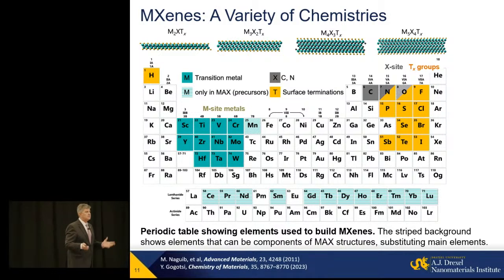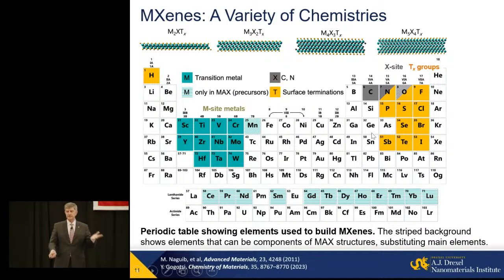Now, what are MXenes? They're layered materials, nanometer or thinner, built of a couple of layers of transition metals connected to each other by either carbon or nitrogen. So we have a dozen transition metals. We can have a lanthanide substituting for one of them. Carbon, nitrogen, oxygen can substitute for, again, carbon, nitrogen, mixing oxycarbide, oxynitride. You can make carbonitride. You can mix and match those elements, and transition metals will not stay non-terminated. They will pick whatever is in the environment, synthesis, or you can replace elements, and you can get halogens, you can get chalcogens, oxygen, hydroxyl groups, you can get phosphorus, antimony. We predicted that arsenic can also be there, just someone needs to go and make it.